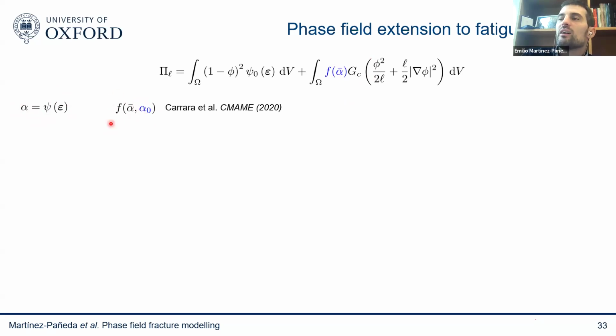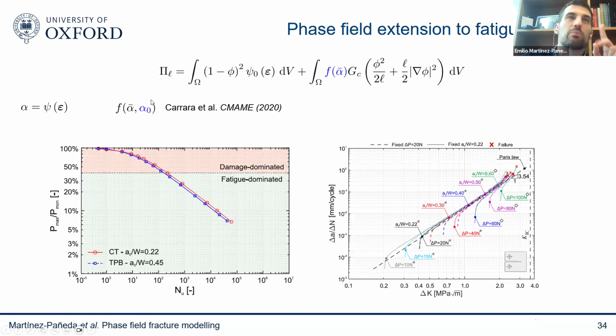You need, well, two part things. You need a degradation law, how a material will degrade for a given cyclic loading history. And that, of course, is material dependent. So you need some calibration with experiments. And in their simplest version, they had a model that relied purely on one calibration parameter. And they showed very nicely that once you calibrate the parameter, you're able to capture both SN curves and Paris law behavior as an output of the simulations.